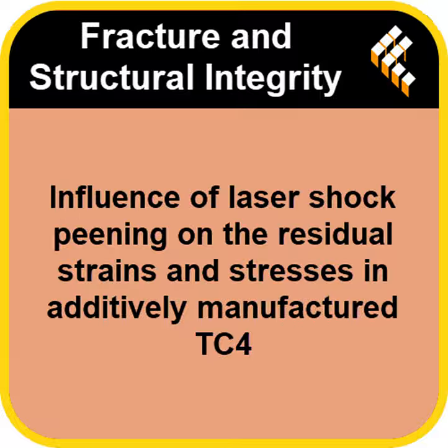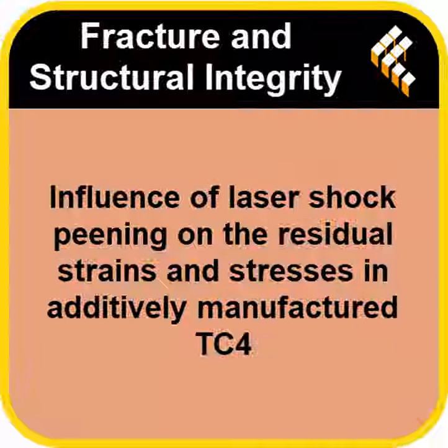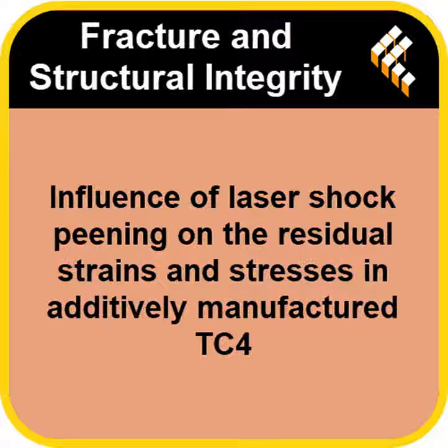The directionality. Yes. They found the initial residual strains in the samples cut along the build direction, the z-axis. Okay, vertically upwards. Were almost 10 times greater than the strains in samples cut along the printing direction, the x-axis, across the layers. 10 times. Yeah, just based on how the part was oriented during printing. Yeah, nearly an order of magnitude difference in the inherent tensile stress. That's a huge deal. It shows how critical the initial AM setup is for the part's baseline state. That really highlights the built-in flaw aspect.